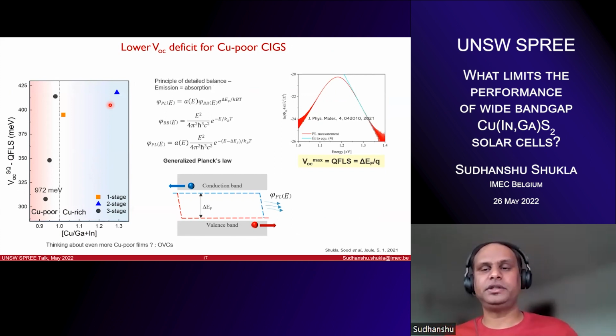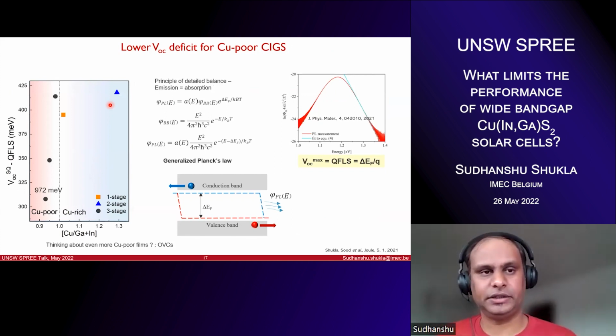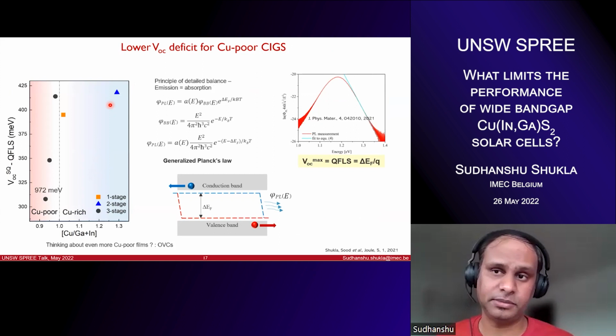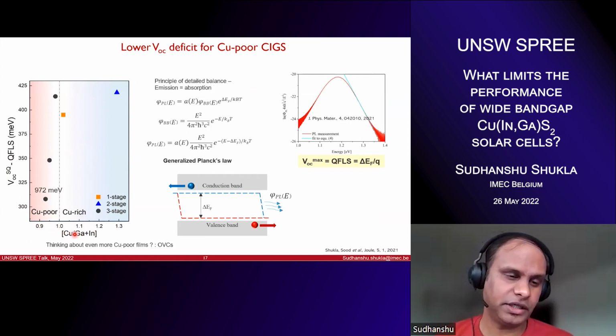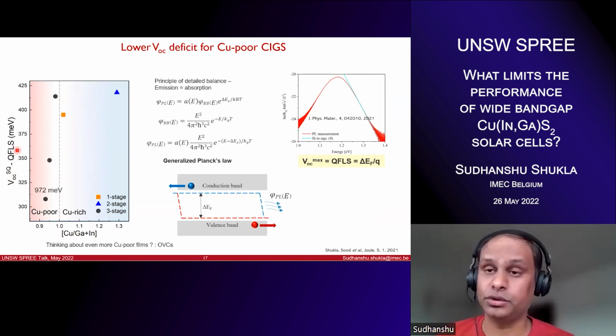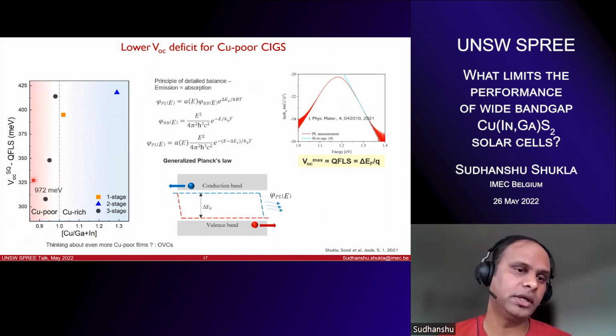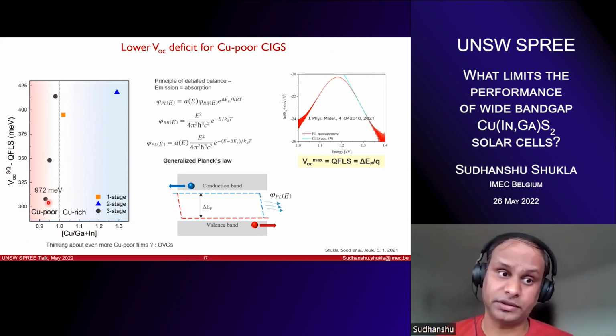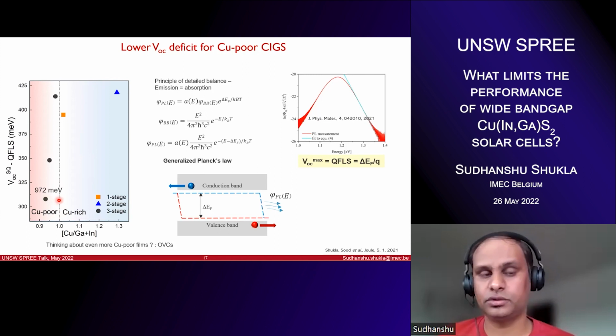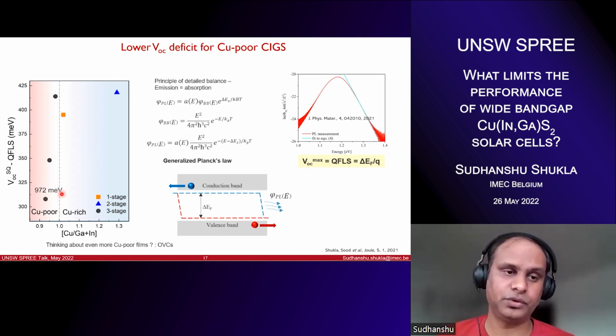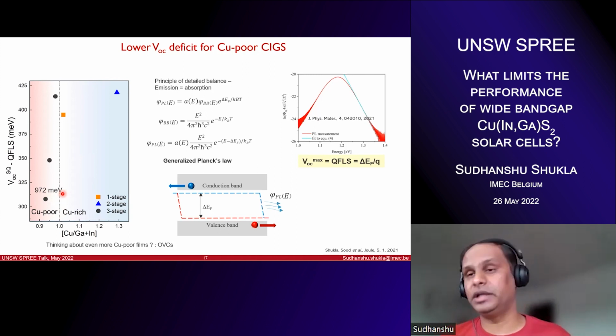So as you can imagine, when you have a lower deep defect, as I said, you would expect higher quasi-Fermi level splitting and therefore higher VOC. This is exactly what you see in this plot on the left, which tells you that if you go more and more copper poor, your VOC deficit with respect to QFLS or band gap, if you want to, improves. So it reduces. And the highest quasi-Fermi level splitting we saw is for the absorber with 0.93 stoichiometry, so CGI of 0.93, which was about 972 meV.